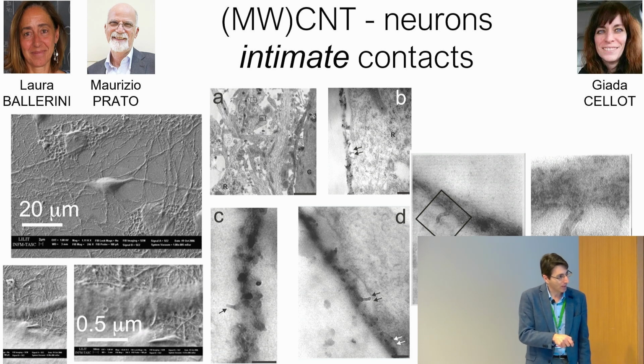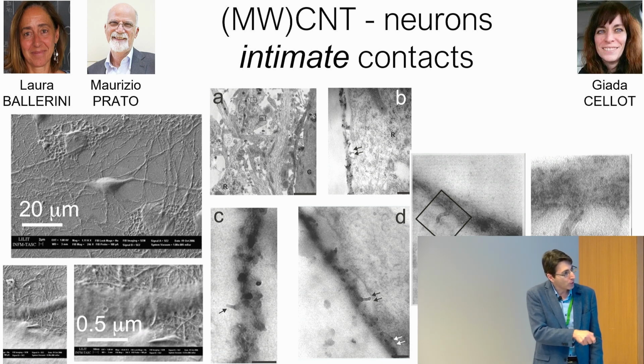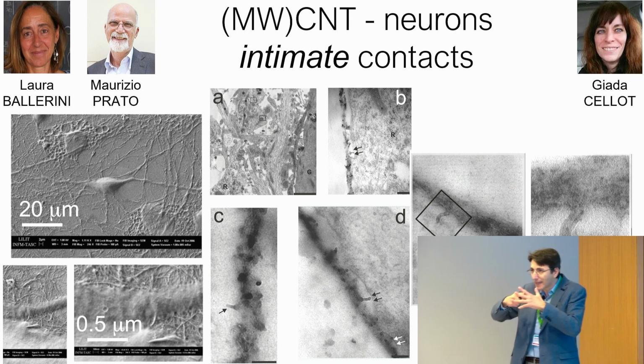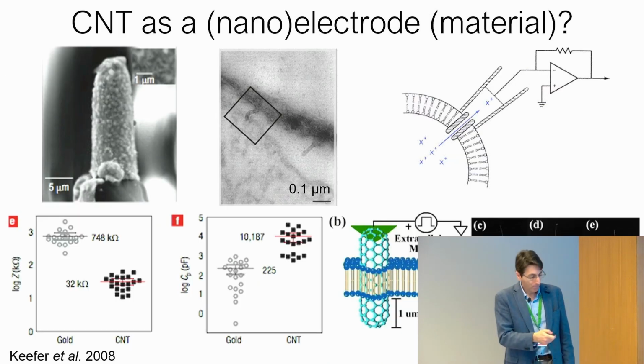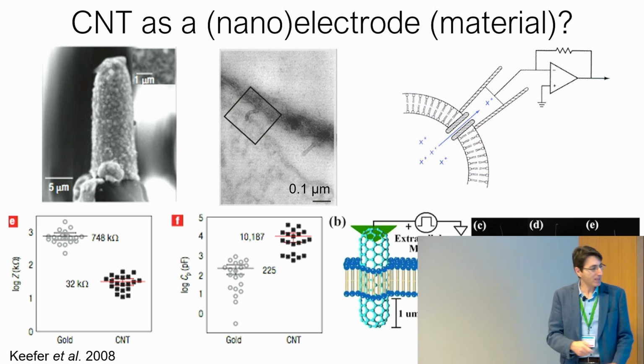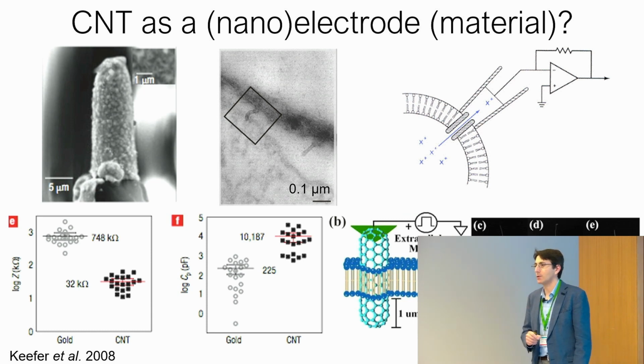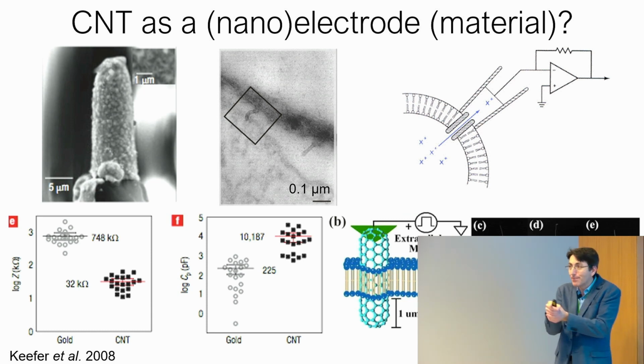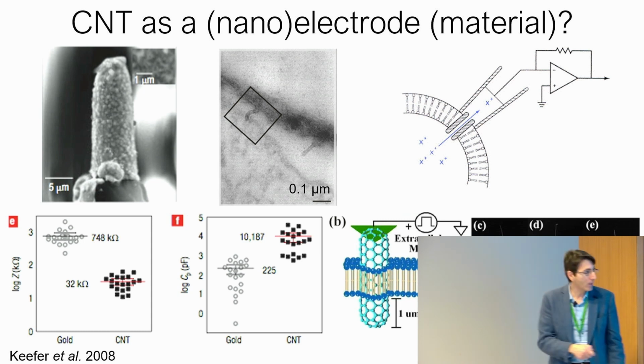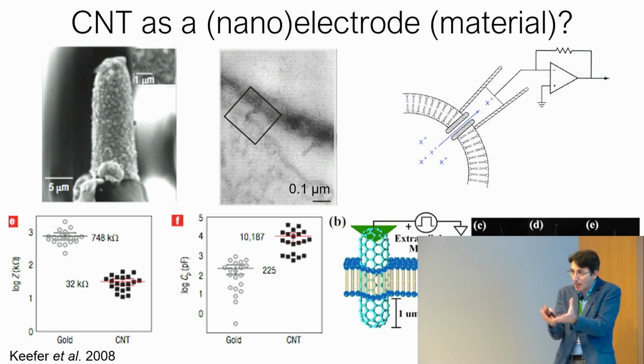This is instead a transmission electron microscope image of a similar condition, a side view, a sagittal section, in which you see the substrate where bundles are spontaneously arising. In this case, these are multi-wall nanotubes, and this is the membrane of a cell, and it seems that these bundles are indeed pinching, penetrating the membrane. There have been very heroic attempts, though I don't think there were follow-ups, in which people mounted a single carbon nanotube on a cantilever of an atomic force microscope and very carefully pushed it through the phospholipid bilayer that makes up a cell membrane.